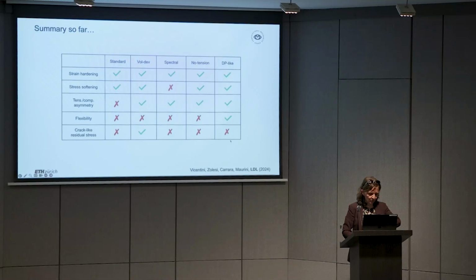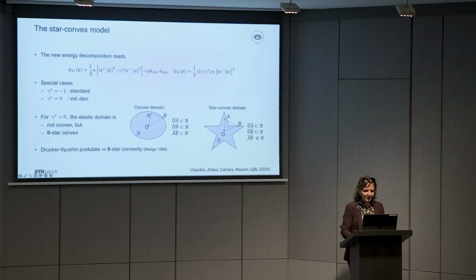So this was the objective of my student Francesco Vicentini. We did this in collaboration also with Corrado's student Camilla Zolesi. So we came up with a new energy decomposition, which is actually a minor change with respect to the volumetric deviatoric split, where we add this term, and this term depends on a new parameter, gamma star, which gives us the flexibility. In fact, this model contains the standard model and the volumetric deviatoric decomposition as special cases.